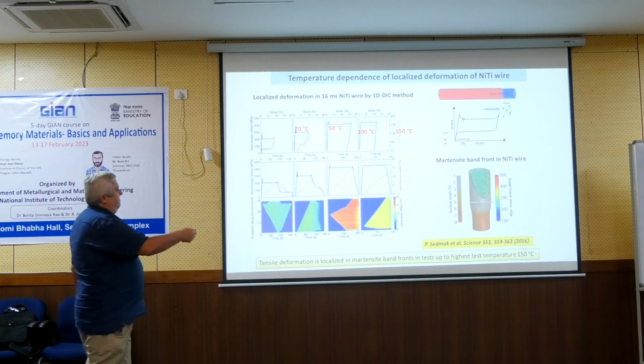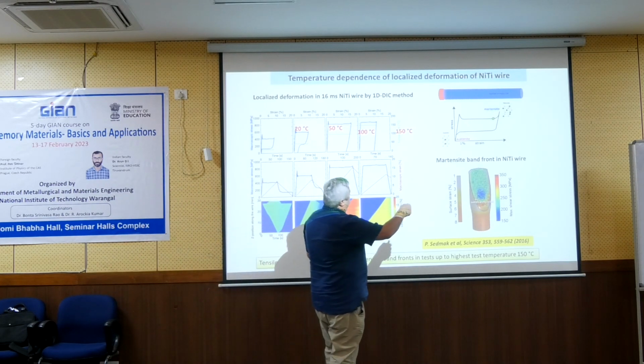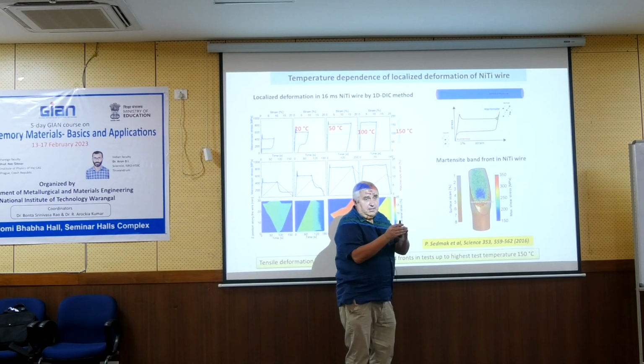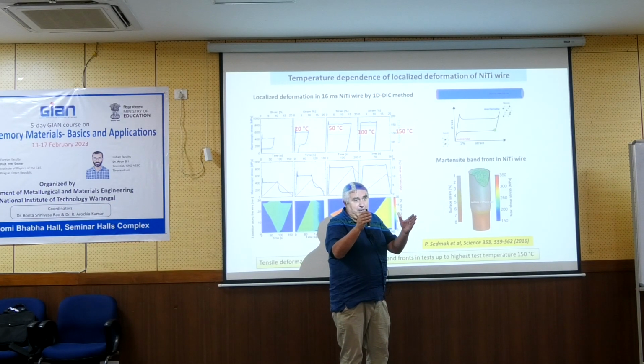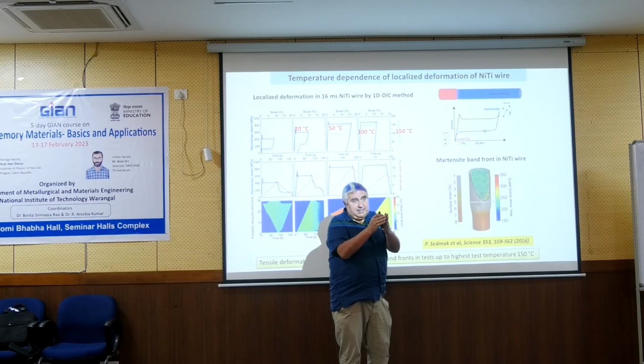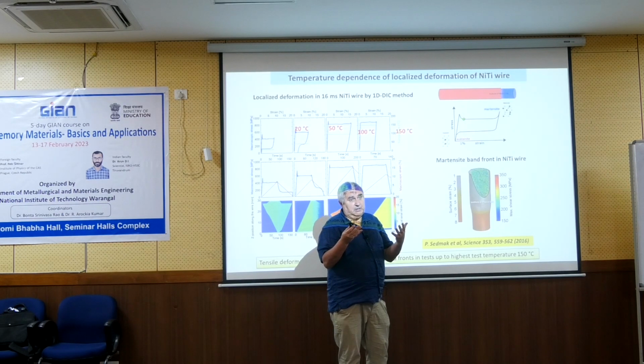Okay, first time to forget about this curve. So if you start to unload here, I need to wait, but it's not a good idea to talk now about partial loading, because if I stop here and unload, it will go back down, but inside the material the strain was 6%. So you apply 2%, but because of the propagating band, some part of the material was deformed up to 6%. So you don't have a partial cycle, in fact, much. You will have the same phenomenon. It is clear. This is the consequence of this localized deformation.